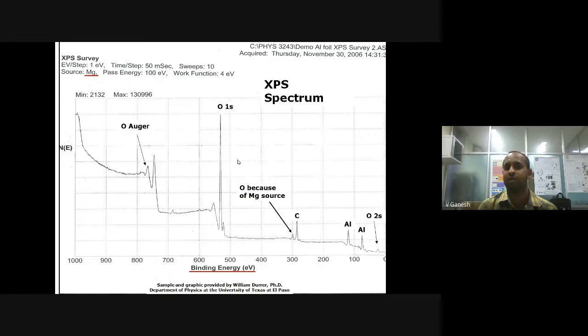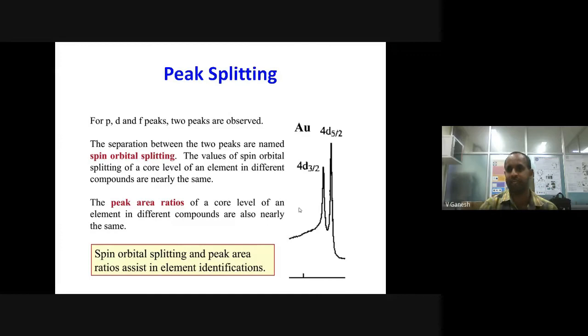For example, a typical 531 electron volt sharp peak would tell the presence of oxygen, and the electron comes from the oxygen 1s orbital. Similarly, carbon would provide about 284.7 electron volt, and this is carbon 1s. So such kind of precise information one would get.